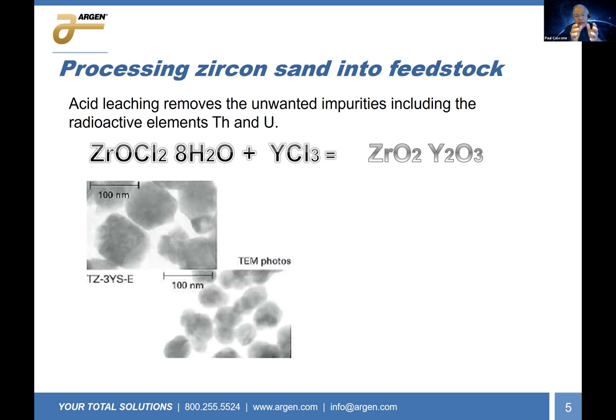So in our case, we add the yttria as yttria chloride right at this stage. And the reason why we do it here is because once we get rid of all the water, the yttria becomes an integral part of the zirconium matrix. And that's what we need. We want the yttria to align with the zirconium matrix. The crystallites that form the zirconia are all nano-sized. You see, this is 100 nanometers here. This is the crystallites that are in the slurry.